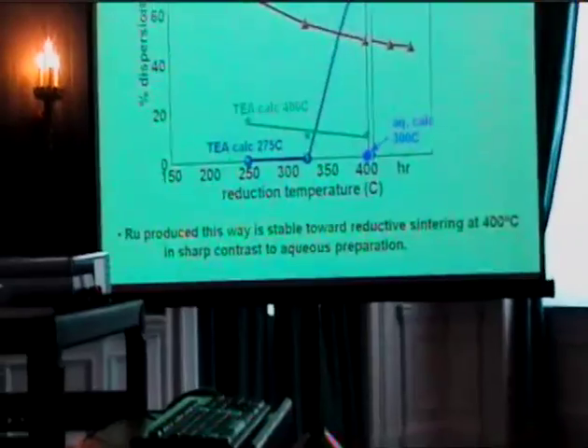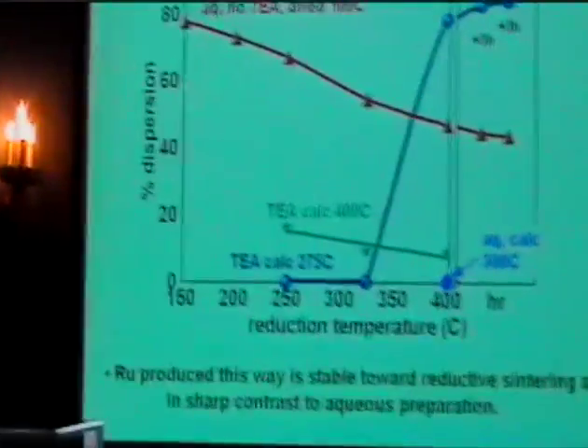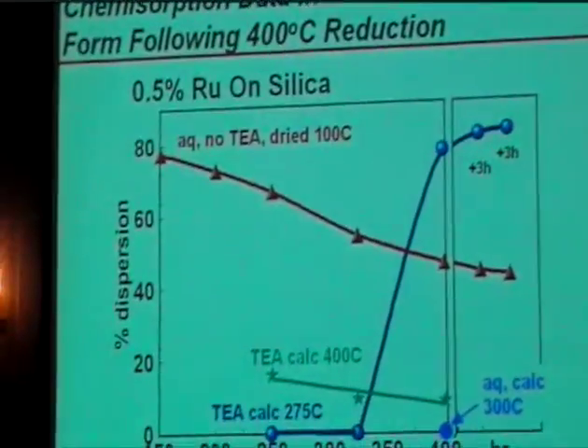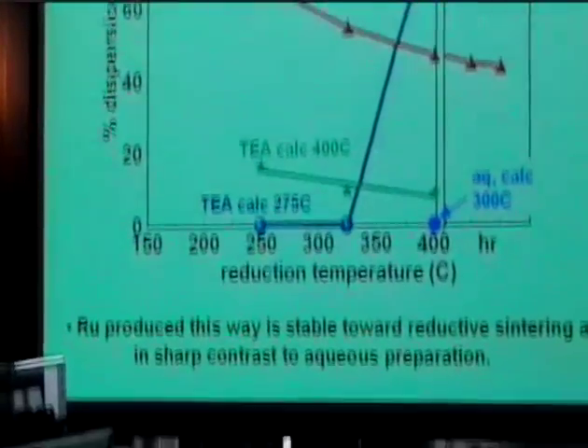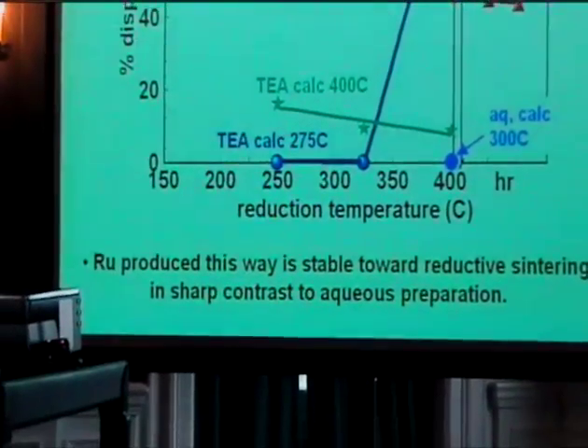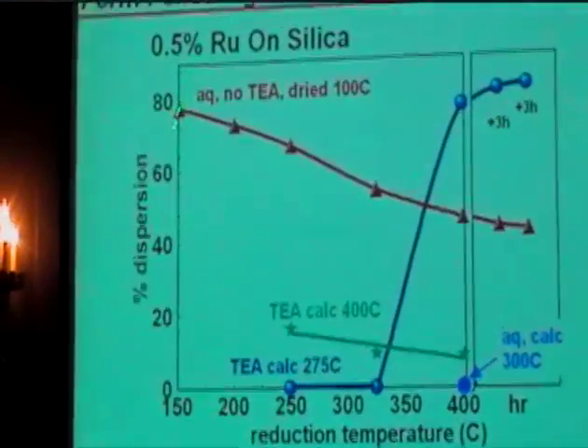This is kind of one of the key things of what we saw here. So I'm going to show you what that was. If you go ahead and just do something simple, take ruthenium nitrate and just impregnate it on silica aqueously. Careful not to calcine it, so you don't go to the oxide, you just have the nitrate there and directly reduce that, you get something with a high dispersion.